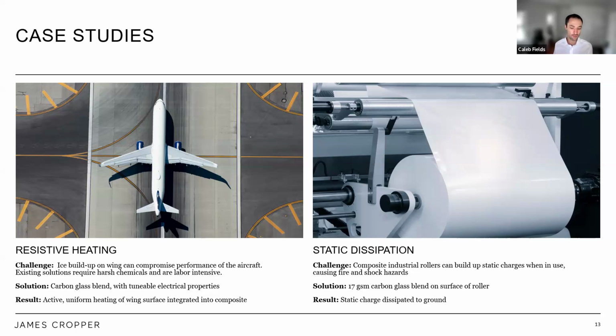So a customer of ours was looking for a solution where they could actively de-ice a plane wing. So we developed a blend of glass and carbon that had the specific resistance that they need for their resistive heating setup. So our material was in the composite plane wing, connected with either a bus bar or a conductive adhesive, and a current was run across it. And it provided active uniform heating of the wing surface for de-icing applications. And compared to a copper wire solution, our materials will provide a more uniform heating of the surface because they are very uniform and cover the entire surface instead of just going up and down like a copper wire would.